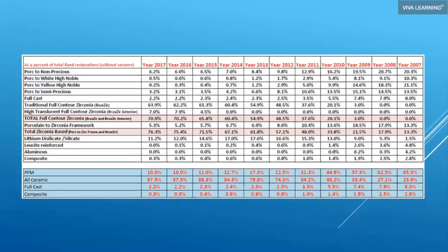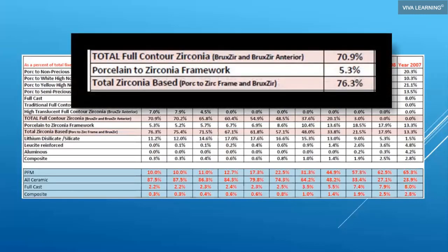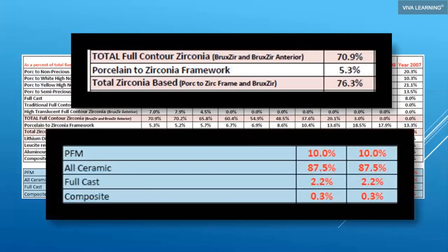So we see where this direction is heading when we talk about crown and bridge. Total full contour zirconia, about 70%. Porcelain to zirconia, 5%. Total zirconia based, 76% of crowns at Glidewell were done with zirconia. And of course, PFM down to about 10%.